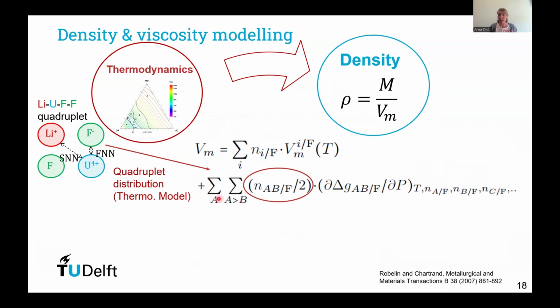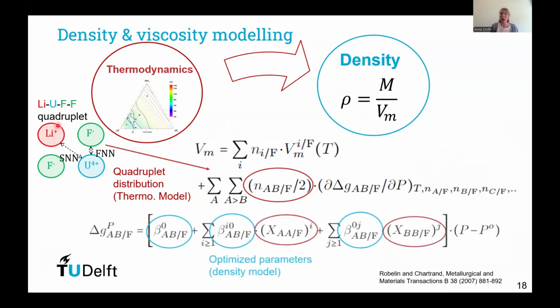So this excess molar volume is related to the quadruplet distribution, so thus is related to the thermodynamic model, as well as to the partial derivative of the excess Gibbs energy with respect to pressure. And this term is really the core of the density model, where we introduce some excess parameters, the beta terms here, which can be optimized and represent then this excess molar volume, this deviation from ideality.